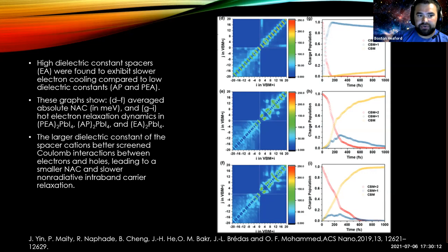And these graphs show the averaged absolute nonadiabatic coupling in millielectron volts and the hot electron relaxation dynamics in the 2D systems with different spacer cations. And it showed that the larger dielectric constant of the spacer cations better screened the Coulomb interactions between electrons and holes, which led to smaller nonadiabatic coupling and slower charge recombination rates, which is, again, desirable. So spacer cations with large dielectric constants seem to be a good idea, at least for this application.